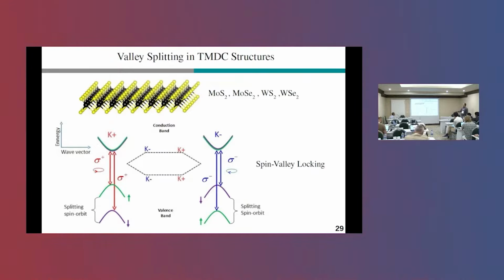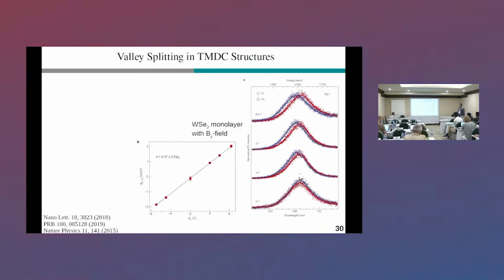And the important thing is, if you do optical measurements, then the plus K valley will react to a sigma plus polarization, and the minus K valley to a sigma minus light polarization. So if you do photoluminescence experiments at 0 external magnetic field, you will find that the PL peaks of the 2 polarizations coincide, right? Because they are energetically degenerate.